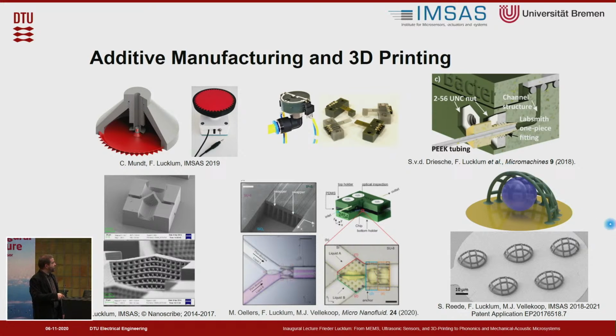And on the micro scale, these are the bottom pictures, we can print even very small and fine details down to a micrometer in size and even below using a technique called two-photon polymerization. The examples here are just a micromixer and a filter in a microchannel. And this interesting example is an ongoing research project still at the University of Bremen, where we build these cage-like structures which look a bit like a football net, but instead of catching a football, we are catching a single biological cell. In this way, we can control where this single biological cell is located on our chip, and therefore can very exactly analyze it, for example using an optical microscope or optical interrogation techniques, or also capacitive or impedance measurements, as is indicated by this light part, which is an electrode.